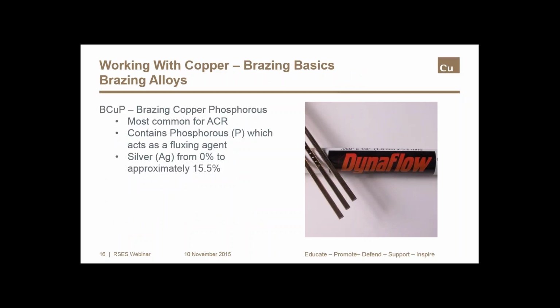Looking at filler metals, there's two basic types normally used in air conditioning and refrigeration applications. There is a brazing copper phosphorus, or B-Cup series, and a brazing silver, or BAg series. The B-Cup series is most commonly used for air conditioning and refrigeration installations, and these filler metals have higher melting temperatures than the silver-containing BAg series. There's a B-Cup 2 filler that's recommended for close tolerances. There's B-Cup 3, 4, and 5 that are recommended for joints where close tolerances cannot be held.